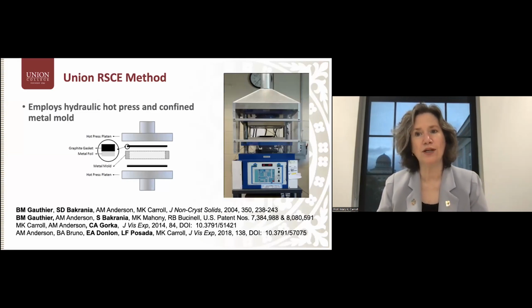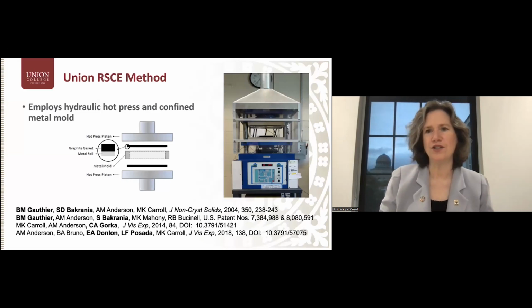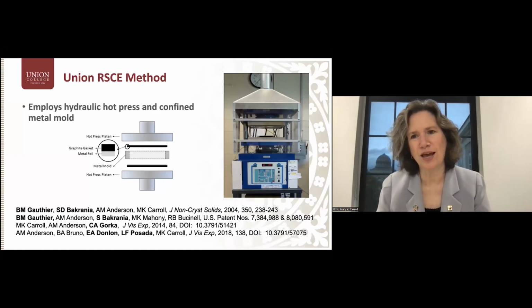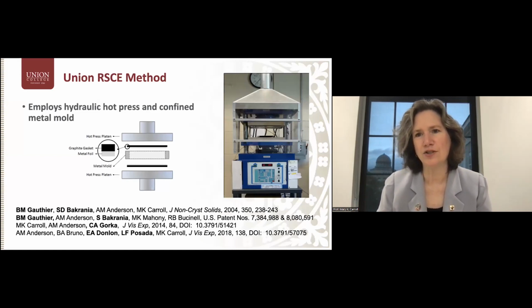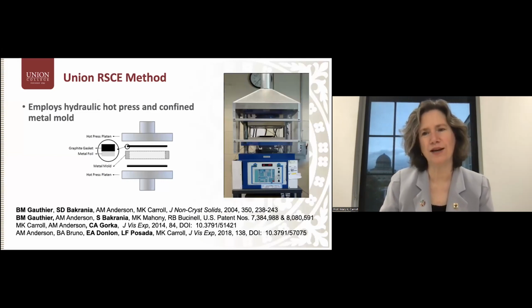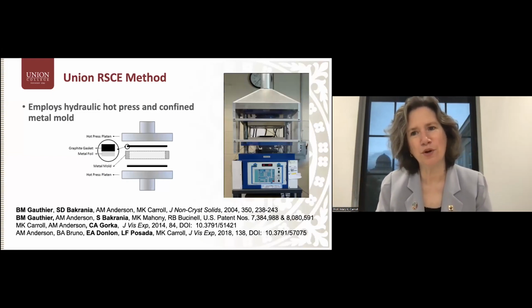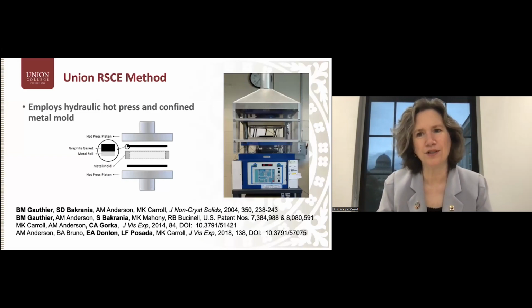There has definitely been work in the literature on the use of aerogels for drug delivery, and as I said, we've had a couple of students do some experiments with that. We are able to entrap, for example, ibuprofen in aerogels using our process. In fact, the ibuprofen is basic, so we could actually use it as the catalyst for the sol-gel reaction, and then we entrapped ibuprofen, and a student was able to show that we could get at least some of the ibuprofen back out of the aerogel subsequently. But it has been sort of a side project for us.